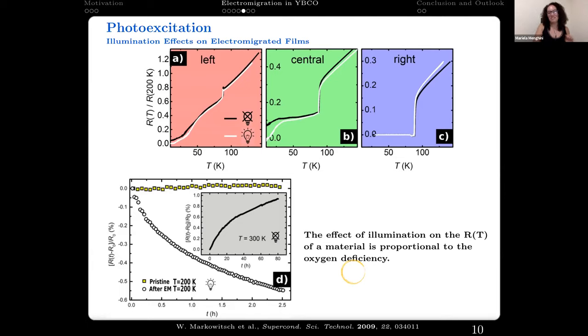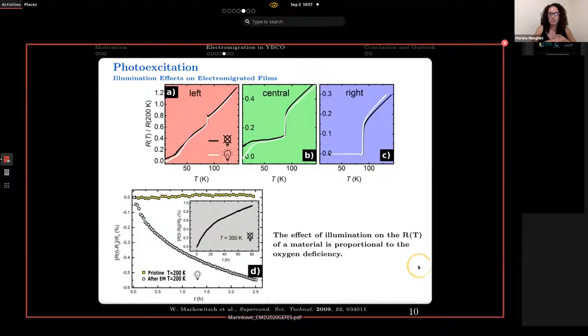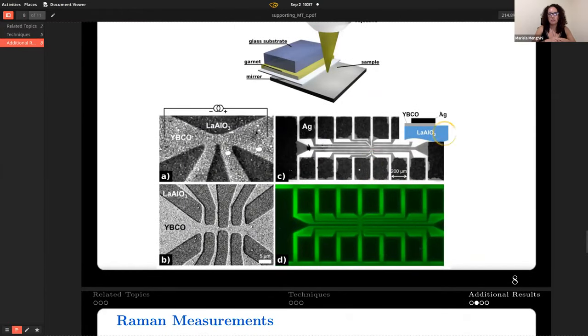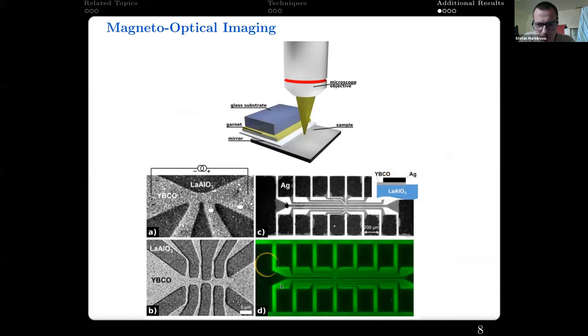Maybe I'll ask one very little one, because you did mention at the beginning that you have done these magneto-optic experiments. So I was just wondering what extra information. Well, we essentially use them to confirm how good a superconductor our films are. Here you can see a comparison between an optical image and a magneto-optical image. The dark parts are low magnetic field, the green parts are high magnetic field. So we see complete expulsion of the magnetic field. And we essentially scan all our devices to see if all of them are good before we start using them.